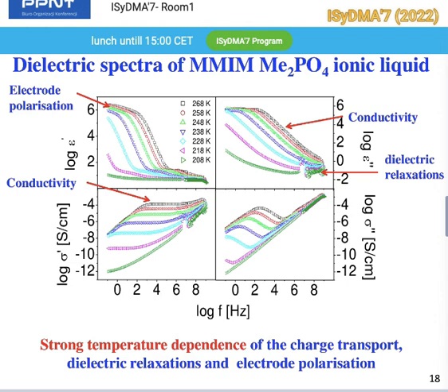This plateau represents the so-called DC conductivity, but this DC conductivity is, of course, not the conductivity at direct current. This plateau is dependent on temperature, as you see here. And the decline we observe here is due to electrode polarization, and this hinders, of course, strongly charge transport. Therefore, we observe here this decline.